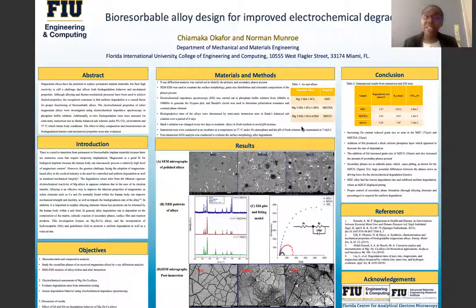Elements under investigation are tabulated here and are denoted as MZC, MZChE, and MZCGd. XRD and SEM analysis were carried out. EIS analysis, which is electrochemical impedance spectroscopy, was carried out in phosphate buffer solution. Biodegradation rates were determined by semi-static immersion test. This test was carried out in an incubator. The medium was Hank's balanced salt solution.